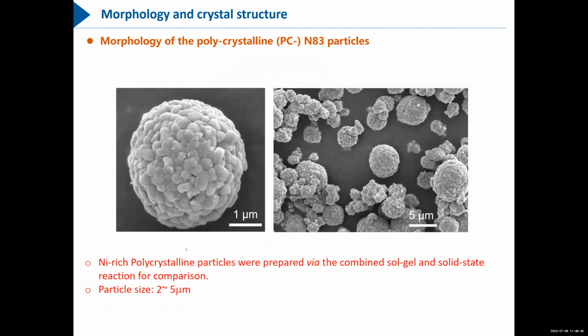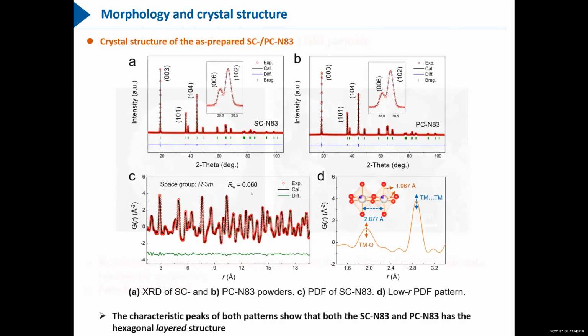In order to study these materials, we have also synthesized some nickel-rich polycrystalline particles by almost exactly the same method, with just a little difference. The particle size has also been controlled to 2 to 5 microns, and this material has also been studied for comparison. First, we used X-ray diffraction, and it found that these two kinds of materials have exactly the same hexagonal layer structure. So that means the morphology won't change the structure. Both of these materials have a hexagonal layer structure, even though the local structures are slightly different.